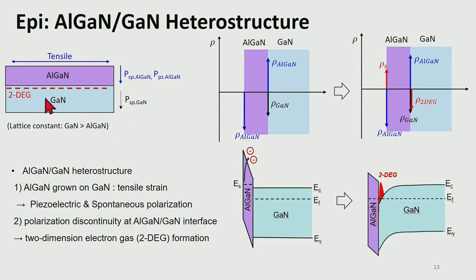So first, both gallium nitride and aluminum gallium nitride have a spontaneous polarization field coming from the wurtzite crystal structure. And on top of that, aluminum gallium nitride has a piezoelectric polarization caused by the strain. So if you draw the net polarization charges across the heterostructure, you can find that there is a very strong electric field in the AlGaN barrier. And because of this high electric field, the surface donor states can be activated, and electrons coming out of the donor states can fall down to the gallium nitride following the electric field, and these electrons can be accumulated at the AlGaN-GaN interface. So these accumulated electrons are called a two-dimensional electron gas, shortly 2DEG, and it is used as the main channel in GaN devices.